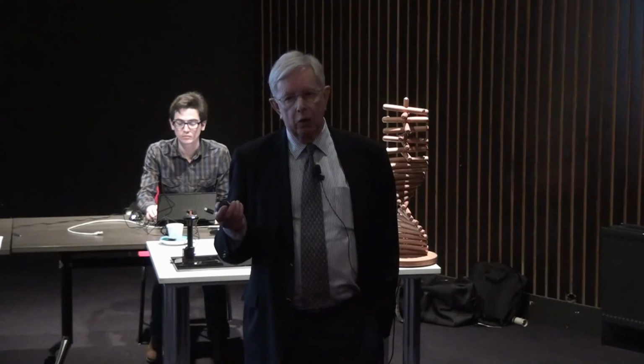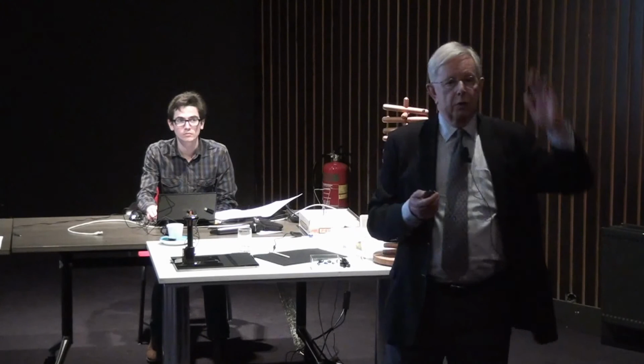And I should say that the modern displays use the effect that I showed you initially, the Freedericksz effect. They no longer use the twisted nematic configuration. They use something called vertical alignment, where the liquid crystal film is, as I showed you, initially vertical, and then it switches to horizontal and then switches back. And that is the Freedericksz effect, and that's what is in all of the displays that you see today.